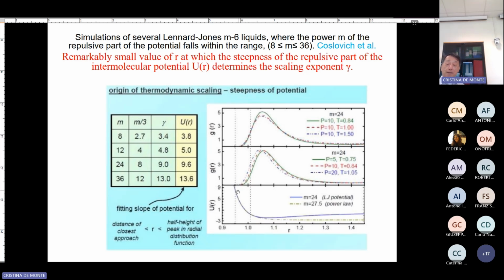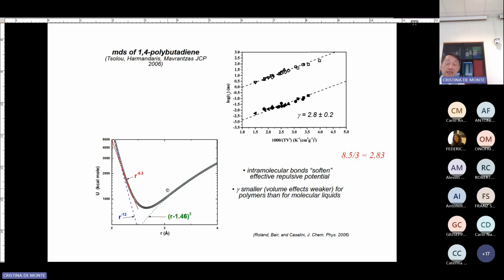You find that gamma is determined by the slope of the repulsive part. It is at very short distance. You see that this is the main peak here, very short distance. It tells you why the JG relaxation already has the TV gamma dependence, because it's already at a short distance. They are determining that, and so I won't go into the details here.